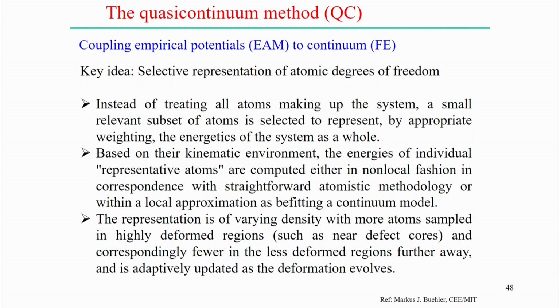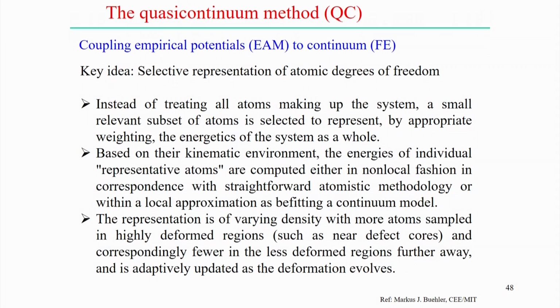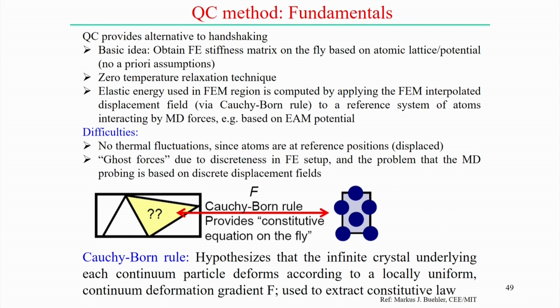Based on their kinematic environment, the energies of the individual representative atoms are computed either in a non-local fashion, which corresponds with the straightforward atomistic methodology, or within a local approximation as befits a continuum model. Since few atoms represent the whole system, the representation is of varying density, with more atoms sampled in highly deformed regions such as near a defect. Strategically, if a high deformation gradient exists, we can increase the number of represented atoms to capture the phenomena more precisely, and correspondingly the less deformed regions further away are adaptively updated as the deformation evolves. That is the basic philosophy of this method.